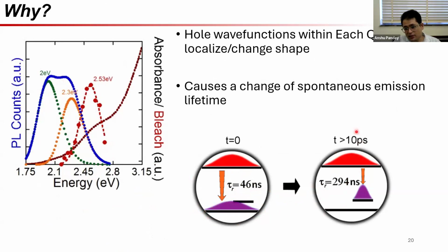But as time elapses, more likely around 10 picoseconds, which is where we see all these changes to be complete in more or less all of the quantum dots, this hole has migrated to a localized state. Now, this is a direct observation of this sort of dynamic and what is happening as a consequence, because now this state represents a totally new kind of transition dipole.